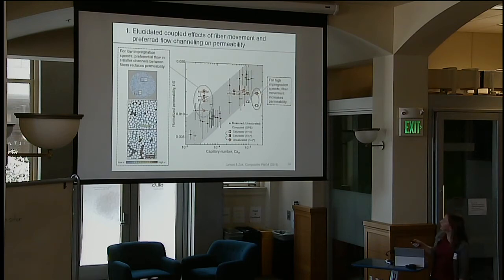And what we found is that at really high flow speeds, which are over here, there's a significant amount of fiber movement, which actually increases the permeability of the fiber bed during fluid flow. Whereas at lower flow speeds, the fluid flows preferentially in smaller gaps between the fibers, forming bubbles in the larger gaps. And this actually gives us a lower overall permeability. So with this knowledge, we can now improve our modeling and optimization of this step of the process.